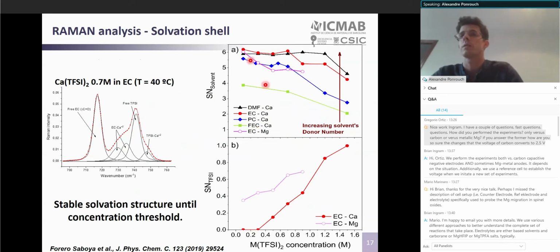So here what you can see is a general trend: as you increase the salt concentration, as expected, you start to form more and more contact ion pairs in the primary solvation shell. But the threshold concentration at which you start to form these contact ion pairs is strongly dependent on the solvent, the nature of the solvent, and the donor number of the solvent. It's more difficult to form contact ion pairs with a high donor number solvent molecule.